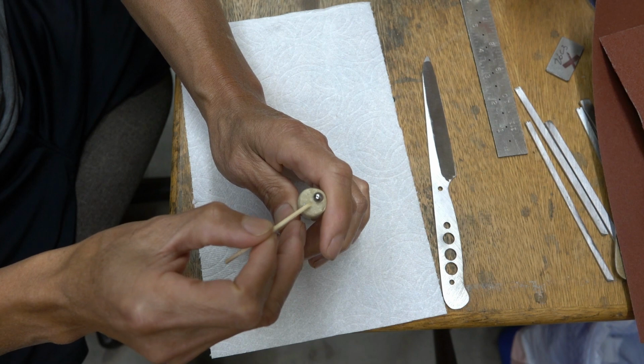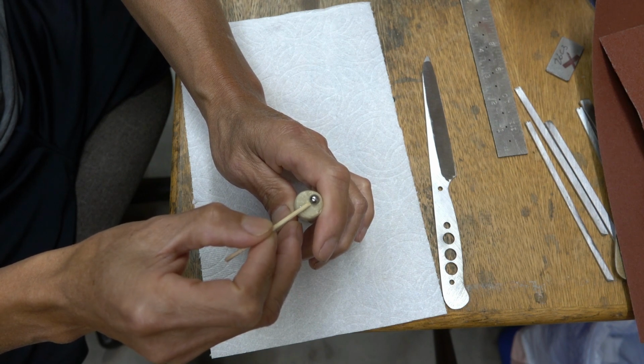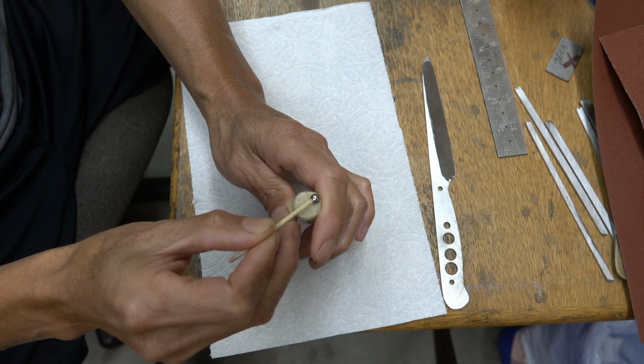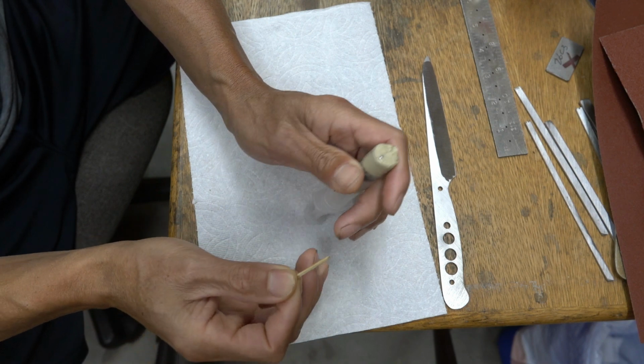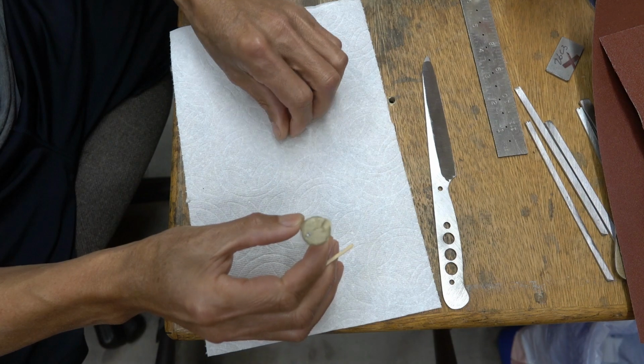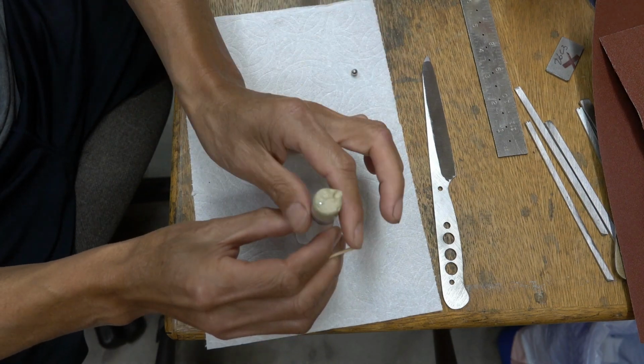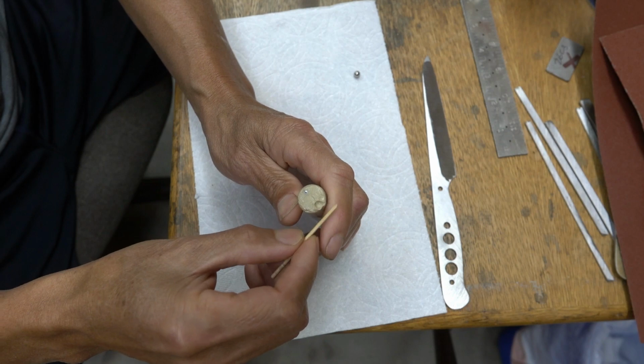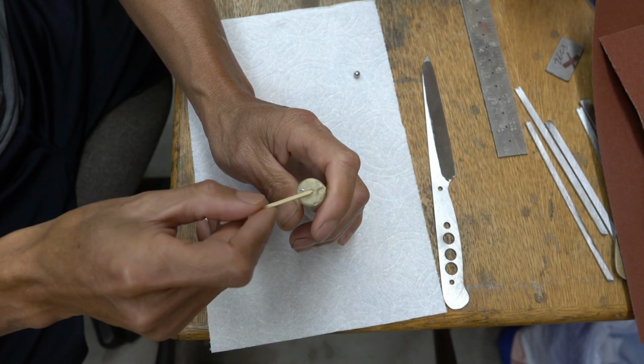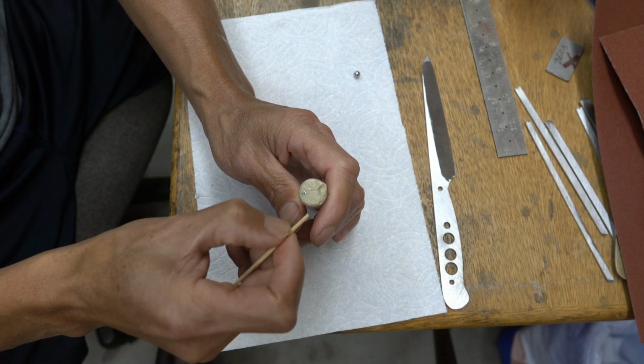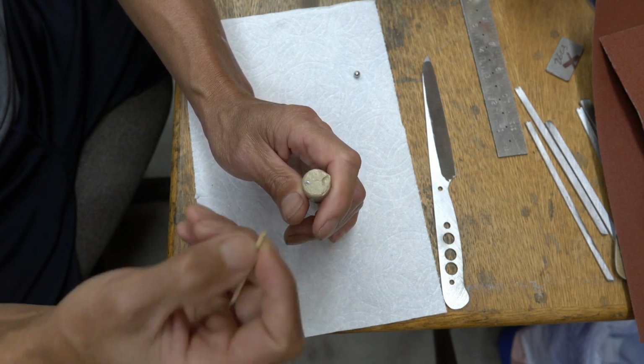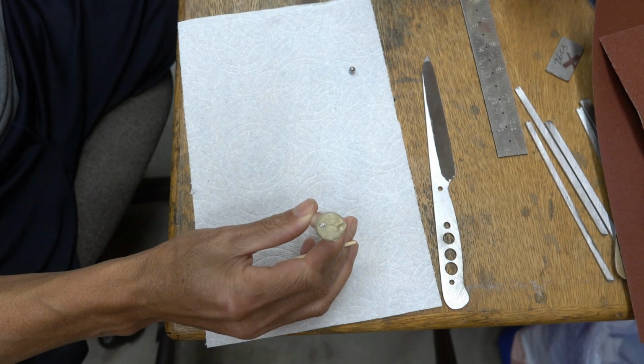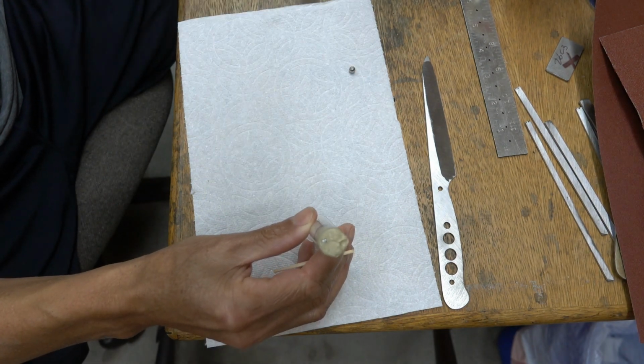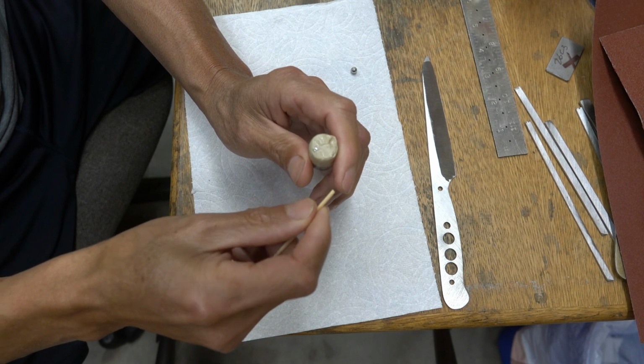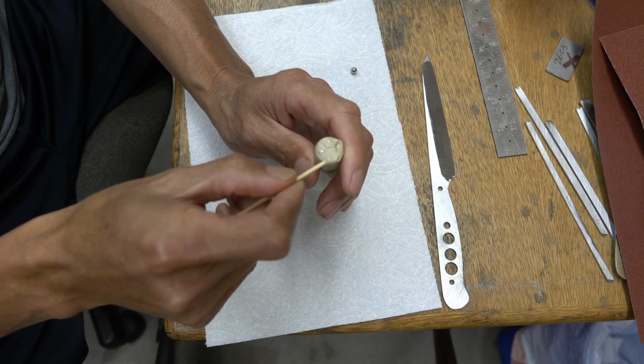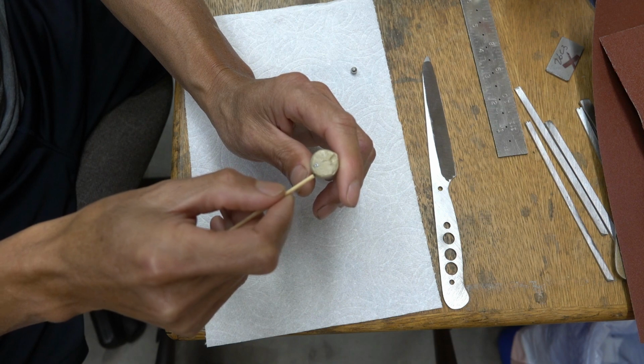Now I'm going to simulate the motion for you to see. If this carbide was protruding this high, the first thing is it will get knocked loose and knocked out of there by the fixed abrasive, and it all depends on how strong the fixed abrasive is. Think of the abrasive, the ceramic, protruding from the sharpening stone, with a part embedded in there. And if it ran into the carbide, then the abrasive also gets dull.